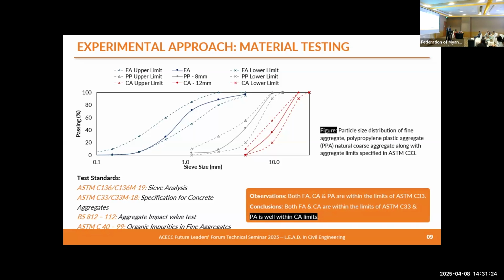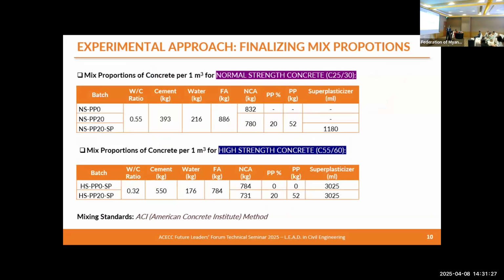So moving on. These are the trial mixes that we derived for our C25/30 normal strength concrete and C55/60 for our high strength concrete. For the normal strength concrete, first we tried without a superplasticizer, because for normal strength concrete we rarely use superplasticizers, as we can get the workability and strength without one. But due to the rough surface of the plastic waste, the workability was not achieved as we expected. So that's why we incorporated the superplasticizer, so that we can get the workability at the same time.